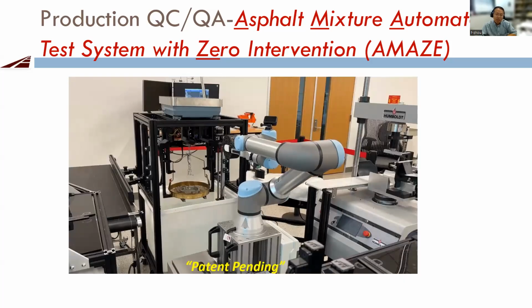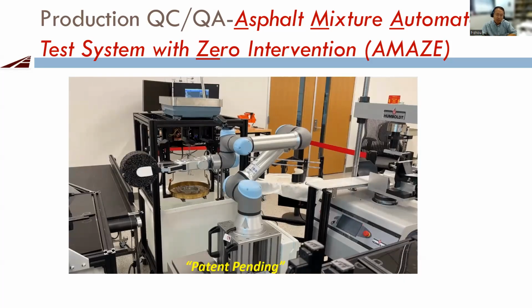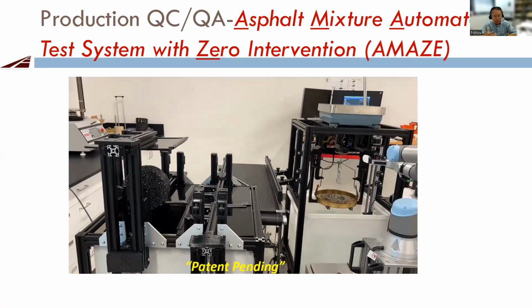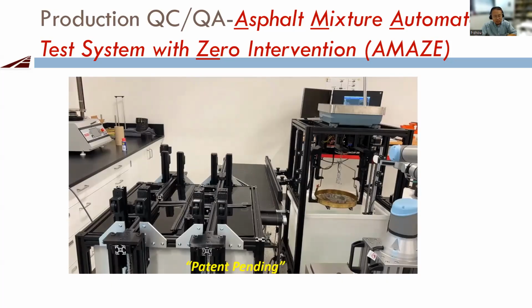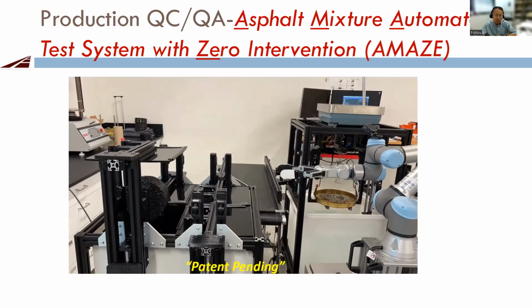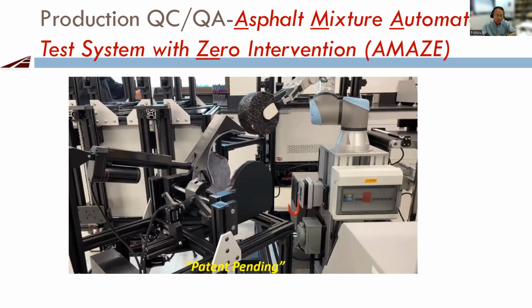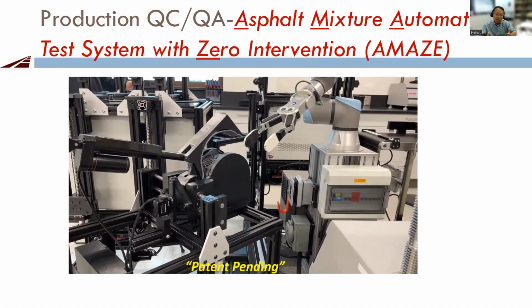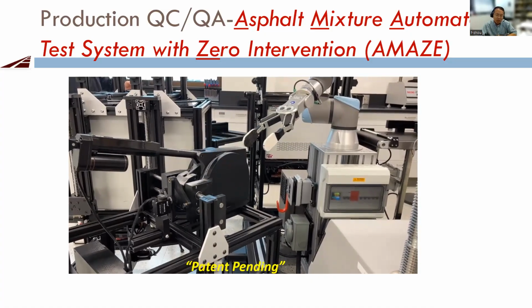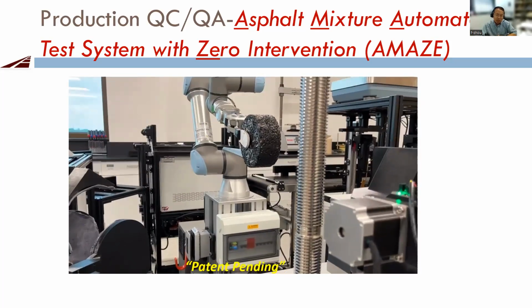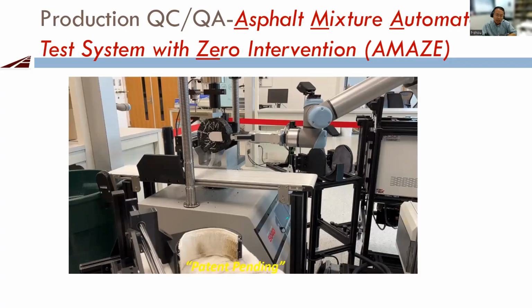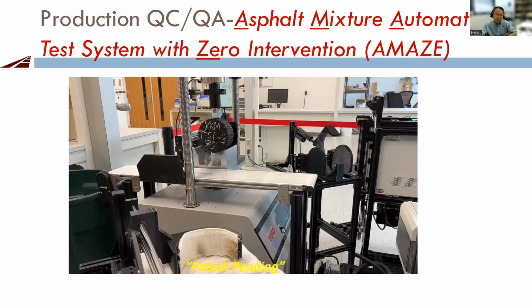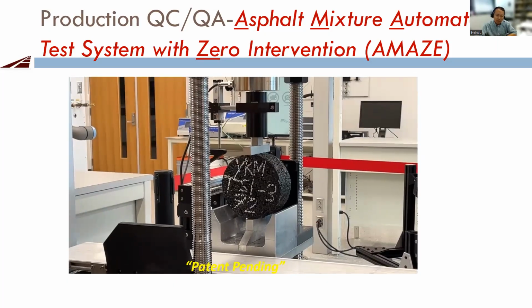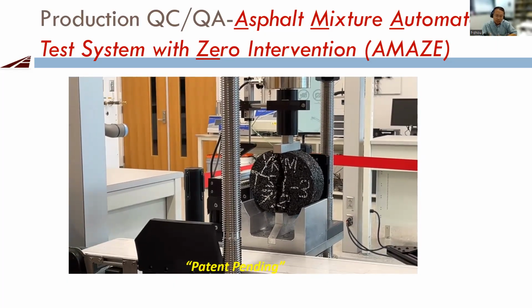So this is the second one. In the previous specimen, after we get a sample, we directly test it. But this one, we want to condition it, because in order to make the test temperature accurate, we want to condition it in the water bath at 25 degrees Celsius. And then we have a quick dry. We really don't want the water dripping everywhere. So we quick dry the specimen, they pick it up and run the IDEAL-CT test again. The same thing, we can run the IDEAL-RT test, but this one they are just showing the IDEAL-CT test again.